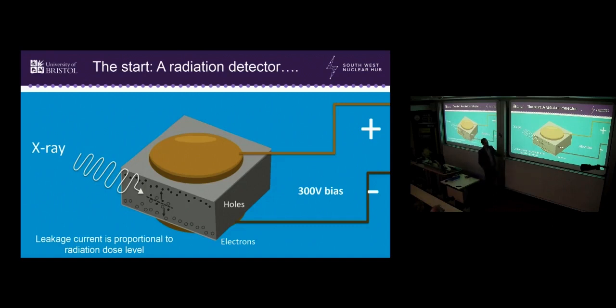So we have electrodes on opposing faces of the diamond. This is a single crystal, typically about 4 by 4 millimeters by 0.5 millimeter thick. I'll show you a picture of one in a minute. And we put it into a very high gamma flux, and we put a 300 volt bias across. And what happens is the diamond detector generates a current which is proportional to the dose that it's receiving. It's a very, very simple device.